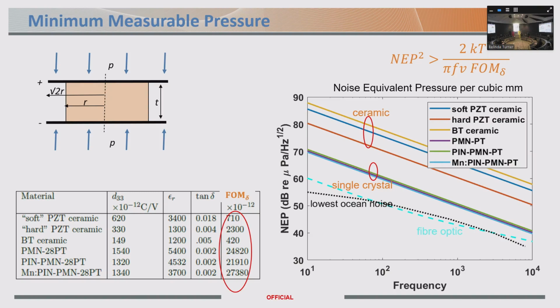external field, right? The point is that if you have a look at this, what this is telling you is that the amount of pressure that you need to exceed the noise for a ceramic hydrophone is much higher than the amount of pressure that you need to exceed the noise for a single crystal hydrophone. So for the same amount of material, these materials can measure much smaller pressures. And if you look at the list of various materials there, and what these figures of merit look like, we're talking about not just a factor of 10 difference, but a factor of 100 difference between conventional standard PZT materials and these advanced materials.